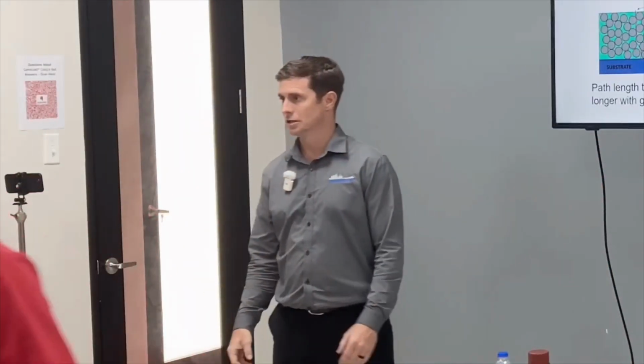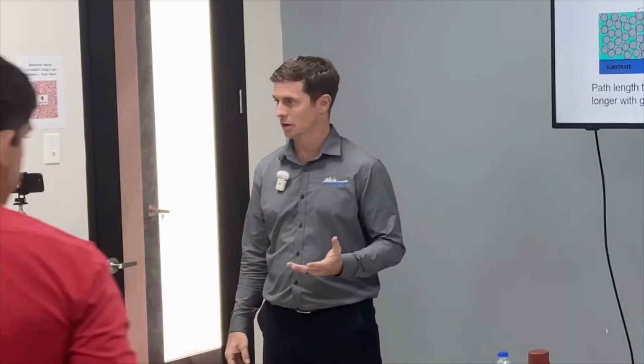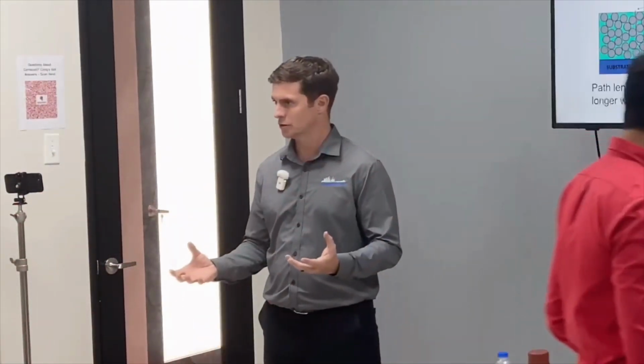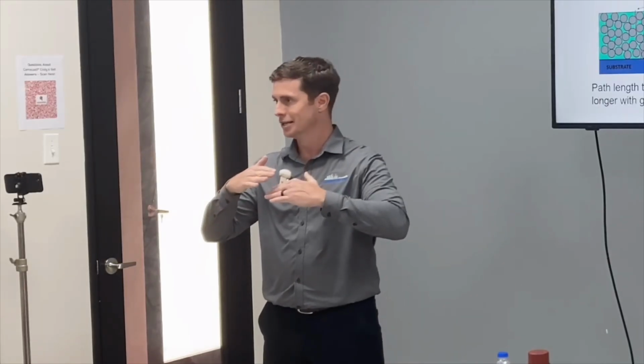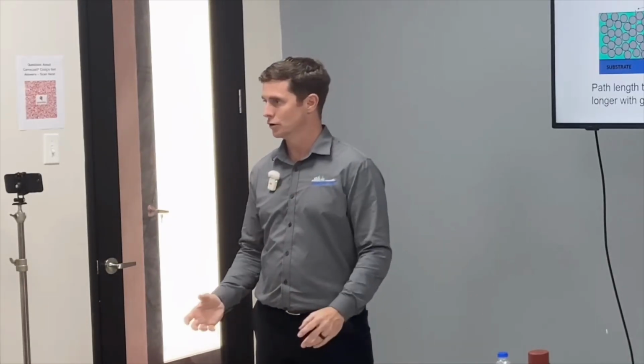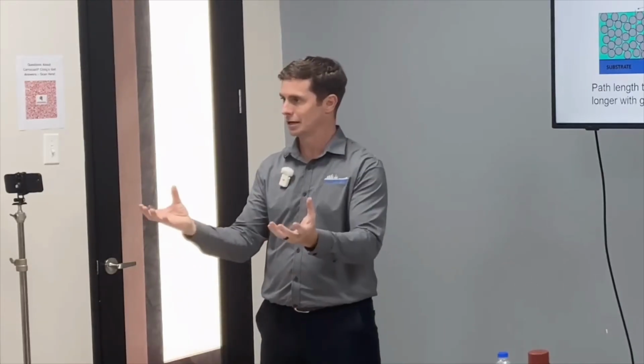Yes, that's a good application of the Corrocoat because the UV will degrade the resin over time and expose the layers. These coatings are highly UV resistant. The resins, similar resins, they don't chalk like an epoxy when you're looking at the unsaturated ester, but the glass flakes actually reflect the light. So yeah, you could make your existing FRP pipe last much longer by prepping the surface and then coating it.